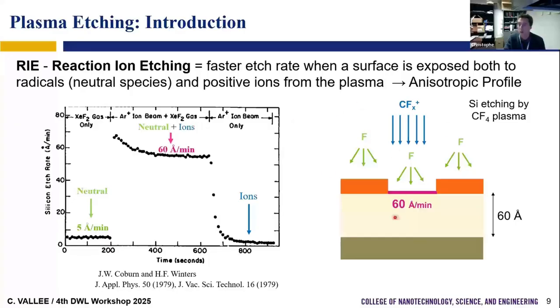This is how we can have an anisotropic etching. I can take an illustration. Imagine you want to etch silicon with a fluorocarbon process. For example, when you have both ions and fluorine, you etch at 60 angstrom per minute.